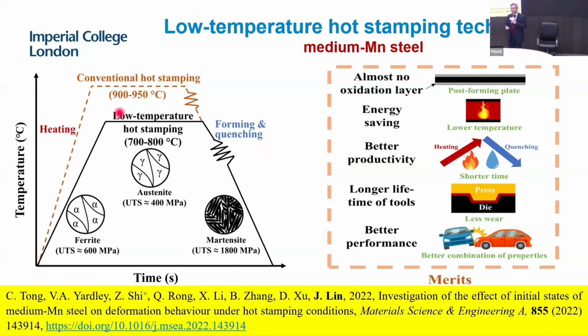Generally speaking, for these technologies we increase the temperature to about 900 degrees C to get the steel into the austenite state, then we form it in a cold die and do the quenching. But I'm not going to give more detailed technologies. If anybody is interested, you can look at our published papers, and we have published many papers over the years on this. But we think 900 degrees C is too high a temperature, with oxidization, surface problems, and so on.